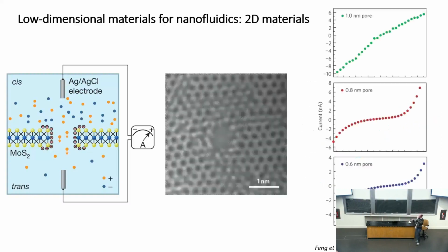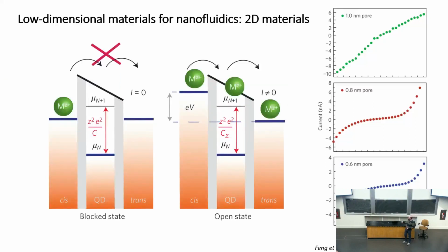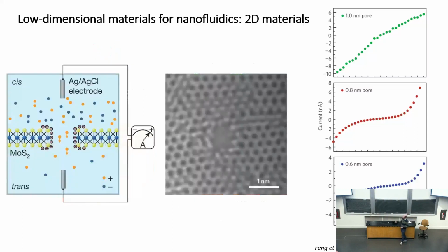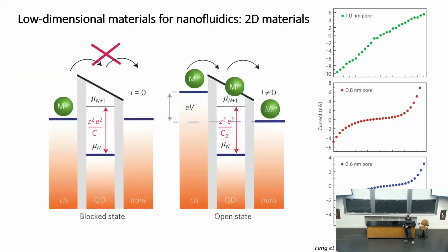But if you make this pore extremely small, at some point you transition between a linear regime and a nonlinear regime, and nonlinear regimes are very unusual. What the authors suggest here is that what they see as the signature is ionic Coulomb blockade, an analog of what's known in electronics, where whether you observe a current or you don't depends on the charge of the island, which is governed by the surface charge on this pore in the very center here.